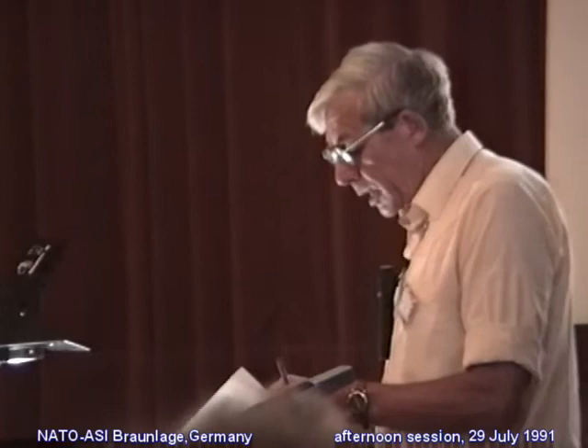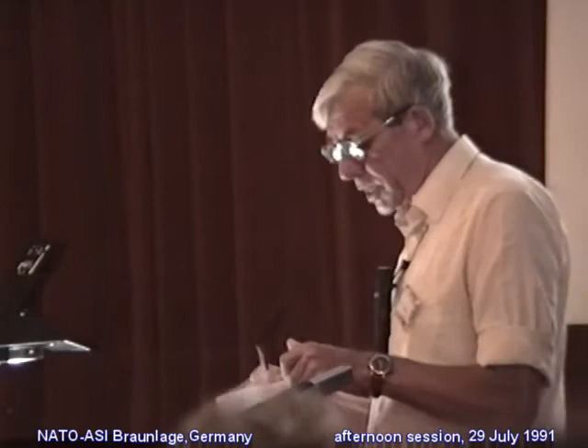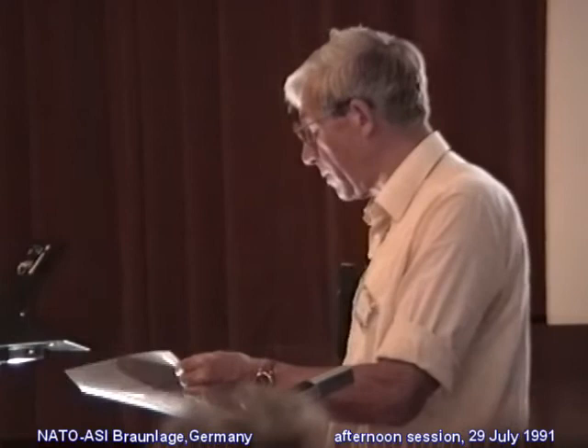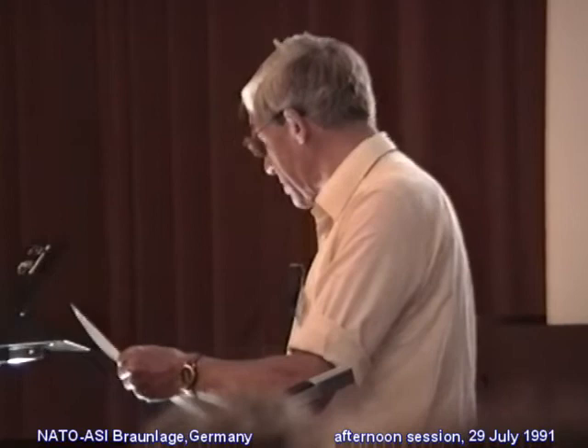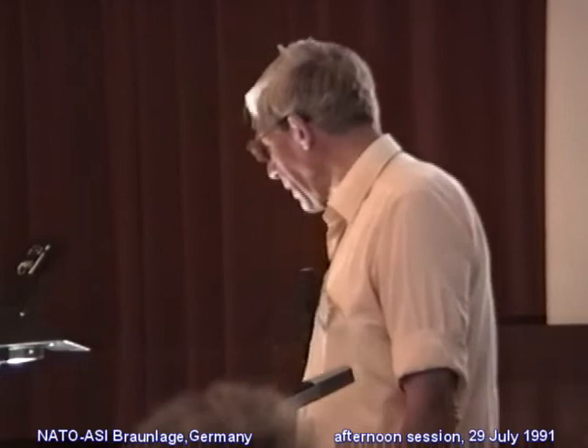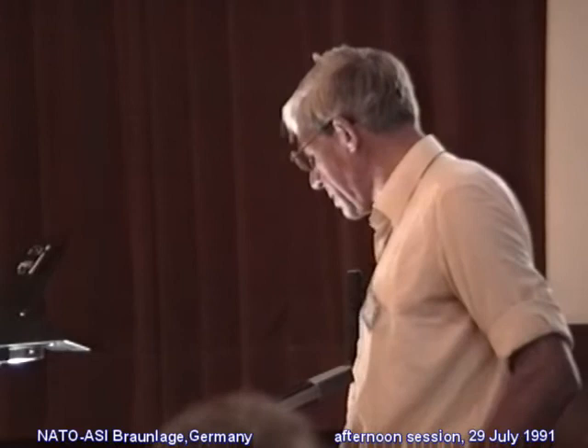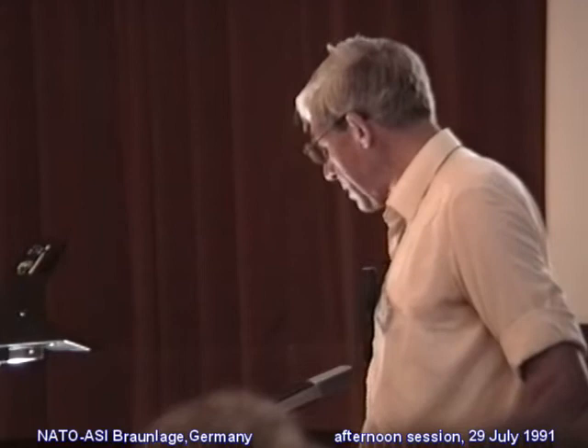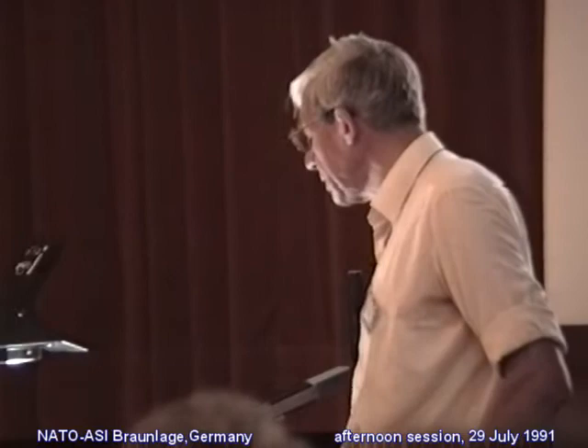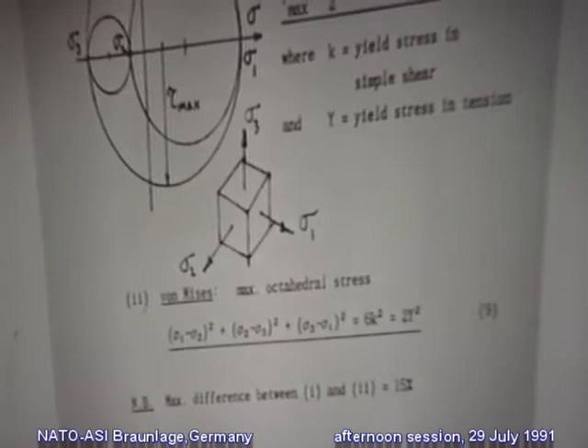I'm just going to say a few words in conclusion about what happens when we exceed the elastic limit. It is a stress concentration, and therefore we would expect to yield rather easily from what David Taylor said earlier. It was almost taken for granted that, at least on the asperity scale, one was going to have plastic deformation. The point at risk where plasticity starts is that below the surface where the shear stresses are high. And if we know the elastic stress field and we have a criterion of yield, then we can calculate the contact pressure and normal load at which yield will first start.